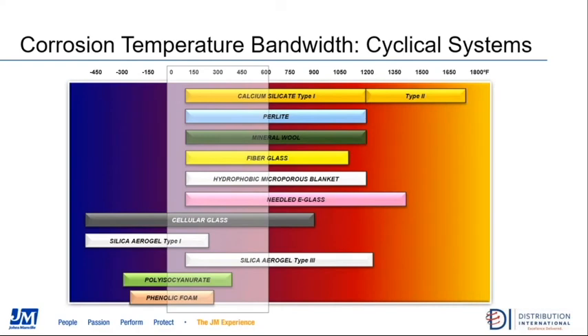The other area we want to talk about is a little bit of a broader temperature range, and this is going to be below zero up to about 600 degrees. So we're going to call this the extreme risk category, and this is going to be for cyclical systems. So any system that is running both hot and cold, or simply a system that cycles hot and then at some point in time gets cycled down, turns off, and becomes ambient, or, depending on if you live in the Midwest, can go below zero just due to outside air temperature. But this is what we're going to call the extreme risk. So if you've got an application that's either a cyclical system or something that just gets cycled on and then cycled off, you want to make sure you're taking that into account because this is where you're really going to potentially see a lot of corrosion happen.